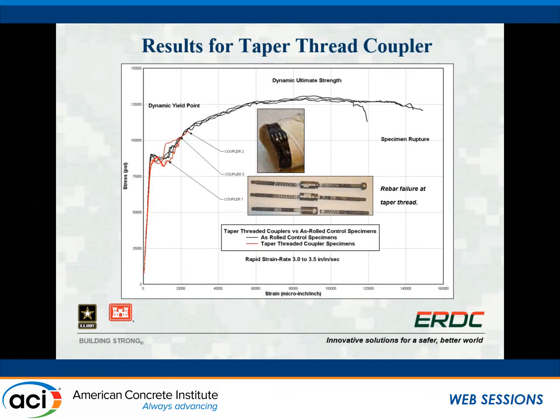I'm just going to show a few different stress strain curves for some of these different systems. These are all obtained in these dynamic tests, so it's a strain rate of 3 per second. You can see these black curves, those are for the baseline material, just the as-received, as-rolled reinforcing bars. For these particular grade 75 bars, the yield strength is about 80-85 KSI, and you get about 12 to 14% ductility.